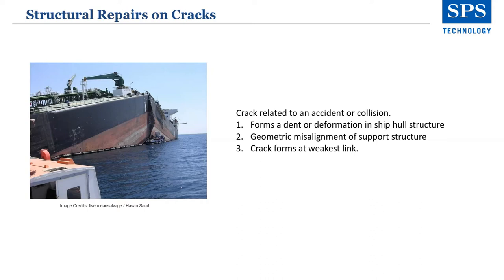Cracks are not easily detectable — they can go unnoticed during routine inspections, especially in the early period of a ship's life when the perception is that the ship is brand new. Once a crack has formed, it spends almost 80% of its lifetime in the region of a short crack before it finally starts to propagate fast, leading to failure. Repair of cracks involves cost and time, and given the ship's chartered commitments, it may not be possible to repair cracks on a priority basis once identified. Under such circumstances, the focus has always been to determine and control crack growth conditions before final failure.